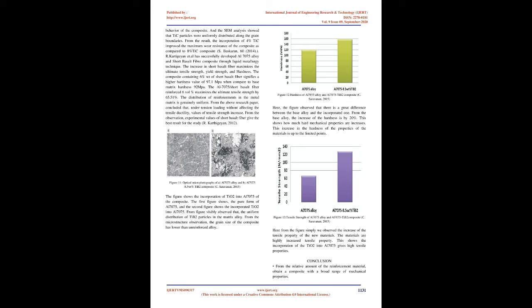Keshavamurthy, 2013. Kumar et al., 2010, studied hardness and abrasive wear behavior with different particle sizes using a mathematical model with the analysis of variance, on Al7075 with 5-25% SiC using powder metallurgy methods. The study clearly shows the hardness of the composites increased with the SiC addition, and micrographs showed uniform distribution of the SiC particles. The abrasive wear behavior clearly indicated the increase in wear resistance as SiC acted as a load supporting element. Composites with larger reinforcement size and high volume fraction displayed improved abrasive wear resistance as compared to other combinations. S. Kumar, 43, 2010.